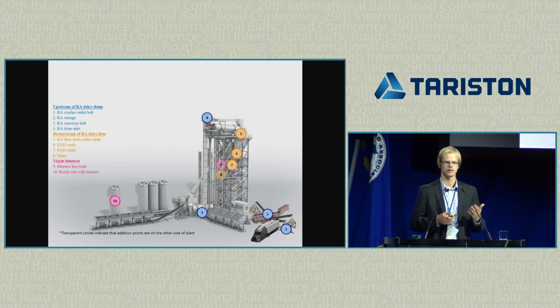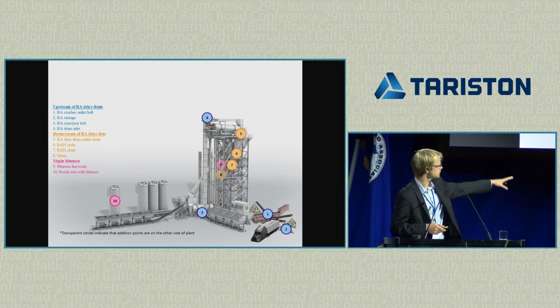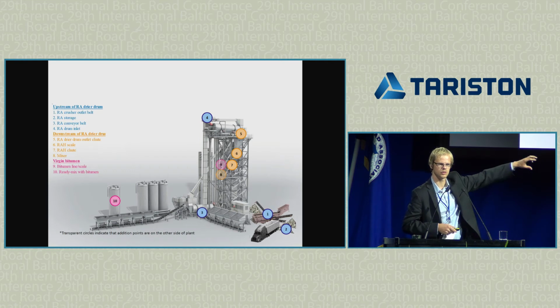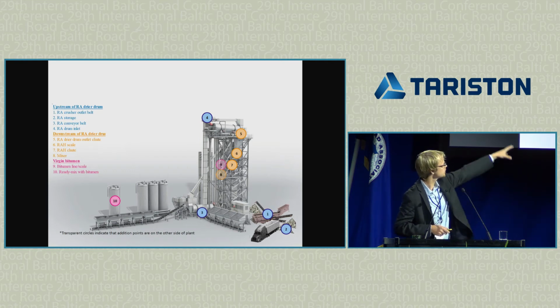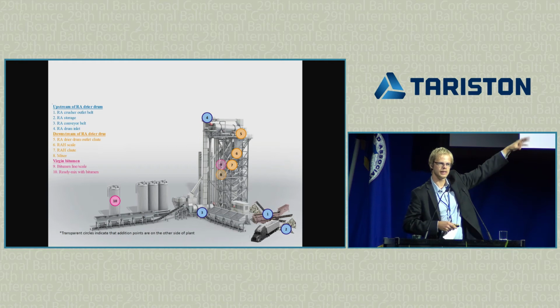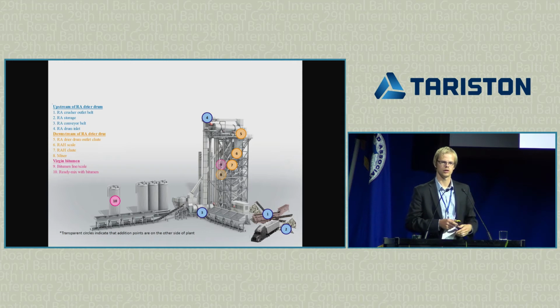We actually went ahead and counted that there are theoretically 10 different locations where we could add the rejuvenator. So you see the blue ones are upstream of the recycled dryer drum, the yellow ones are downstream of the dryer drum, and the purple ones are in the virgin bitumen line. In this example, somewhere where number 3 is, those are the cold storage bins, then the material goes up in the tower, it's being heated there in the hot dryer, and down in the tower there's the mixer.